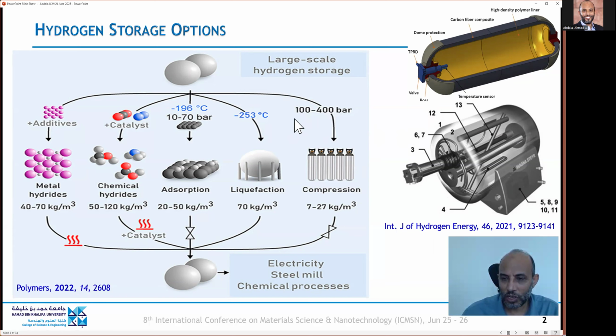To avoid storing at high pressure, we can store hydrogen in a liquid form at ambient pressure, but that requires quite low temperature, about 20 Kelvin. So there will be significant energy loss because of the thermal losses to the ambient condition, which is at significantly higher temperature than the storage temperature. These two physical options provide good storage capacity, but of course they have challenges in terms of cost, safety,